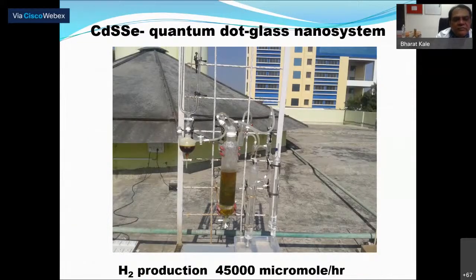Then we made hydrogen on a bigger scale with this glass, because this glass has different band gaps from the UV region to almost the visible IR region. So using this mixture of band gaps, the glass gives huge hydrogen generation due to the absorption of light in the visible and IR spectrum. So we are still working on that, and we wait for commercial application.